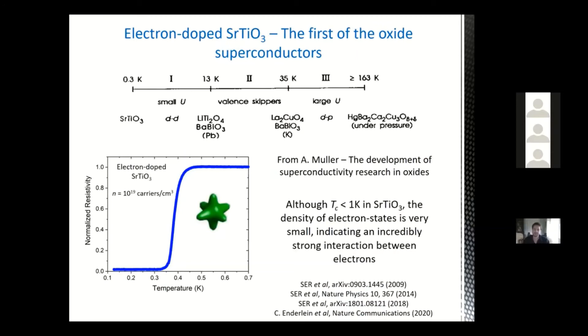Many ferroelectrics are semiconductors with band gaps comparable to silicon. Mobile charge carriers can be introduced by chemical doping or electric field injection. A ferroelectric transition within the metallic state would be an inversion symmetry breaking polar distortion due to a Q=0 soft transverse optic phonon. STEM scans of electron-doped lead titanates show displacement of ions in the unit cell resulting in a polarization. Polar metal states are also observed in electron-doped barium titanate, where increasing charge carrier density gradually suppresses the Curie temperature and the magnitude of polarization fluctuations. Doped STO was the first oxide superconductor discovered in the 1960s, leading to rich development including the cuprates.